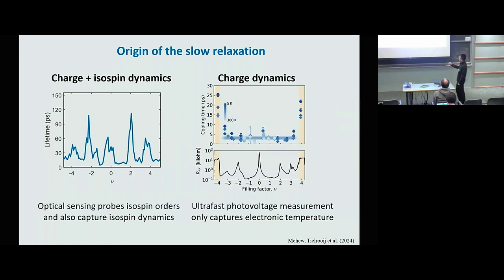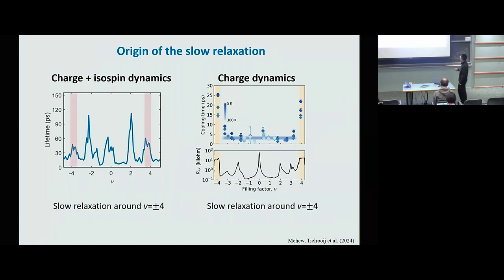So we are looking at both charge and isospin dynamics. And so we can directly do a comparison between these two plots and see which peaks are from charge and which peaks are not from charge. So in this charge dynamics, first what they see is there's a slow relaxation around plus minus 4. That's not surprising because there's a gap there between the remote band and the flat band. This should give a phonon bottleneck.